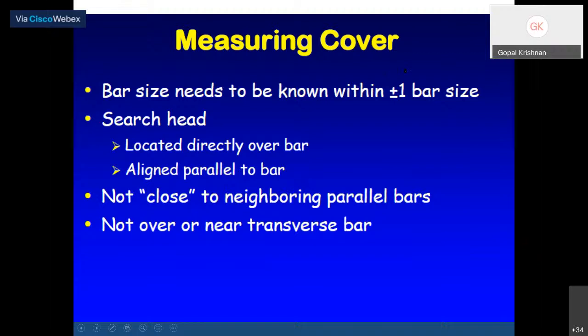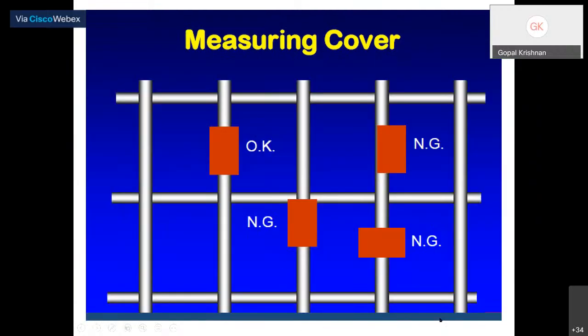Bar size, as I said, you can determine within plus or minus 1. The search head needs to be located directly over the bar, parallel to the bar, not close to neighboring parallel bars or over the transverse bars. Otherwise this will mislead. You can say this one is correct and these are not correct, so we are not measuring correctly.